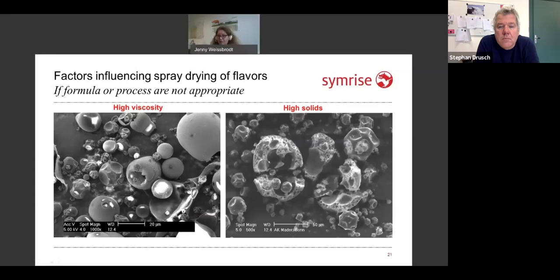Same for very high solids. If you have very high solid content, it can happen that you have a very thick shell very early in the drying process. And then again, your water cannot move out. It wants to come out, it doesn't find a way out. And then you see here, this was a water vapor bubble inside the particle which developed, it wasn't able to move out. And then it led to this destroyed particle.